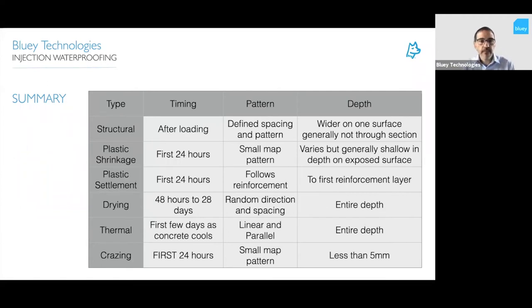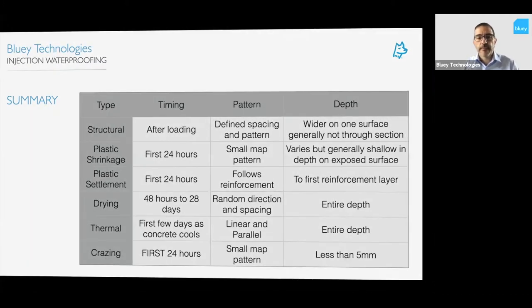So these presentations will be available to download, but I've just summarized there pretty much what we've just spoken about. So the type of cracking: structural, plastic settlement, drying, thermal cracking, when you might see it, type of pattern and the depth. The reason this is important is because these are the questions that you'll ask when you go out onto site or when you see your own structure. When did that crack appear? Did it appear within the first 24 hours? Did it appear after 28 days? Or, you know, did it appear after I loaded the structure? What type of pattern is it? And then from that, we can work out what type of repair method we might be looking at.